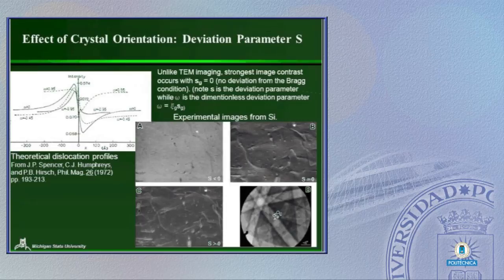One thing that's a little bit different, and those of you who are familiar with TEM realize that the dynamical theory in particular, well, actually kinematical and dynamical theory, both tell us that we want to use a deviation from the exact Bragg condition, and the dynamical theory says we have to do that with a positive deviation from the exact Bragg condition. It turns out with this, we actually want to set up our channeling condition exactly at the Bragg condition.